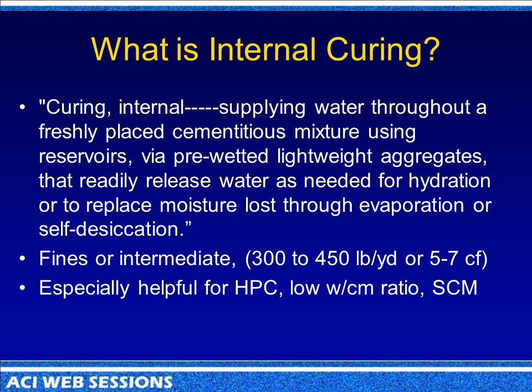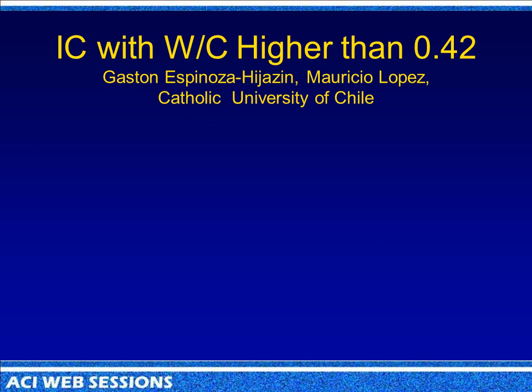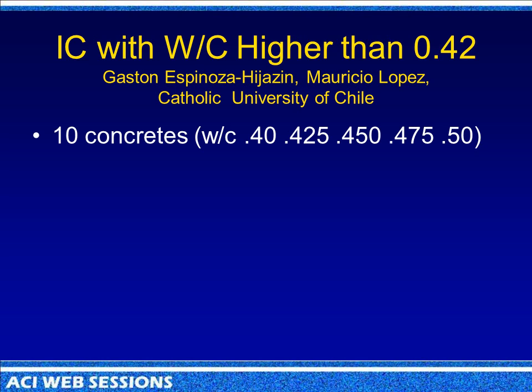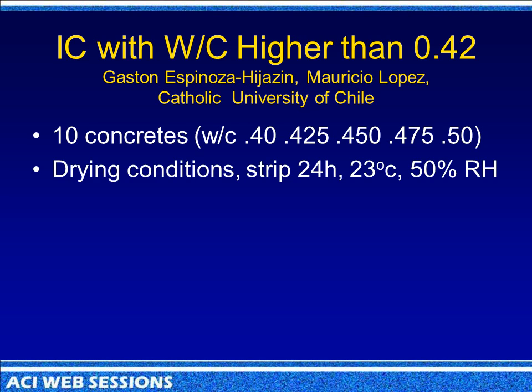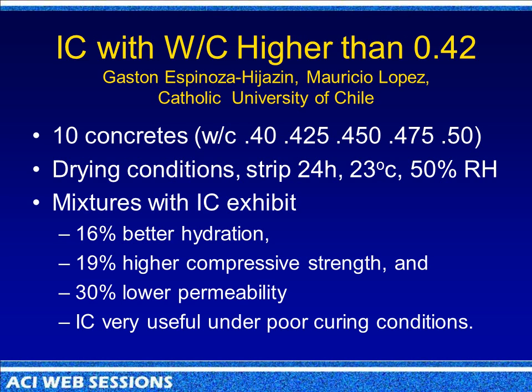And it's especially helpful for high-performance concretes and stuff with a lot of low water cement ratios and supplementary cementitious materials. But it's beneficial for all concrete. So internal curing, here's a great study done down in Chile by Dr. Lopez. I don't know if he's in the room, but he's running around out here. They did 10 concretes, water cement ratios going from 0.4 to 0.5. So these are not high-performance mixes. These are day-to-day mixes. They dried these things at 24 hours. They let them set at room temperature and at 50% relative humidity, and this is what they found.